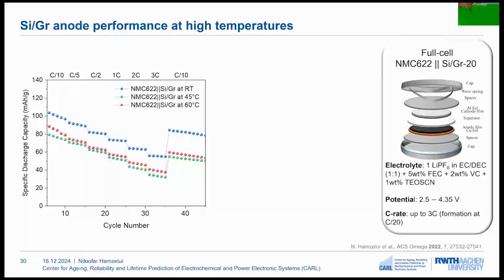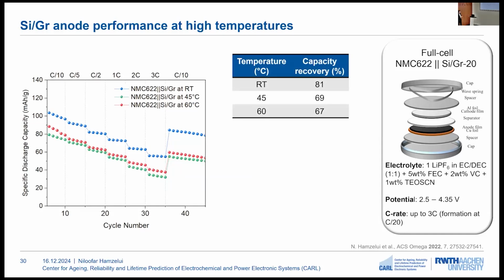Then the electrodes were assembled against an NMC622 cathode in the full cell, and the same measurements were done in the full cell. And we can see that the capacity recovery of the electrodes is lower compared to the capacity recovery that we observed in the half cells.